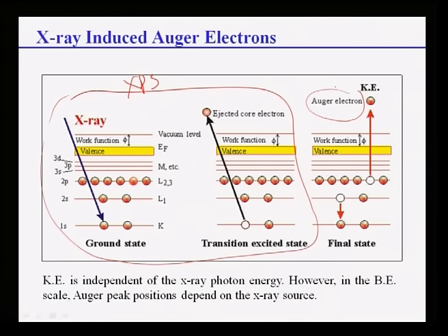So first, let us see how we can identify peaks. Just like X-ray diffraction, here we can identify peaks. So what is the general method? First, check the peak positions and relative intensities of two or more peaks, both in the case of XPS and Auger lines of an element. Check the spin orbital splitting and area ratios of p, d, f.